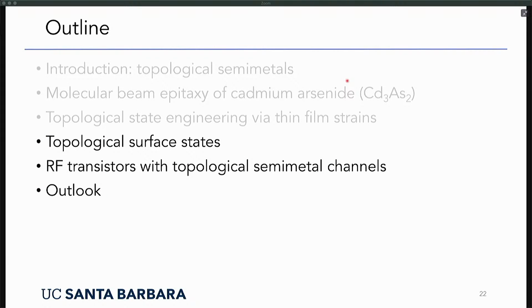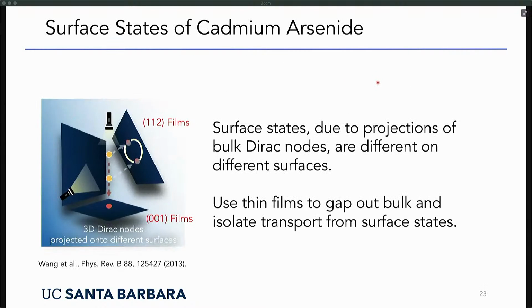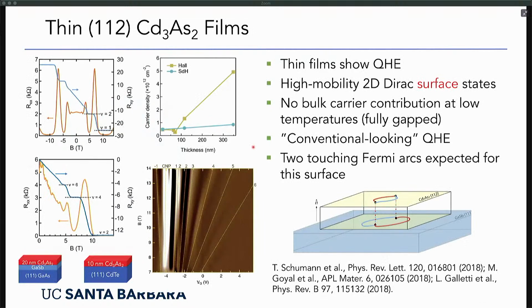So let's turn a little bit to what happens in thinner films. The idea is that we have thin films where we have a gapped bulk, and that lets us more easily, in transport studies, avoid too much bulk parallel conduction, and we can isolate the transport from the surface states. So these are the results shown here. We look at rather thin films of 112-oriented cadmium arsenide, between 10 and 20 nanometers in thickness. And what we observed in this case is a quantum Hall effect.